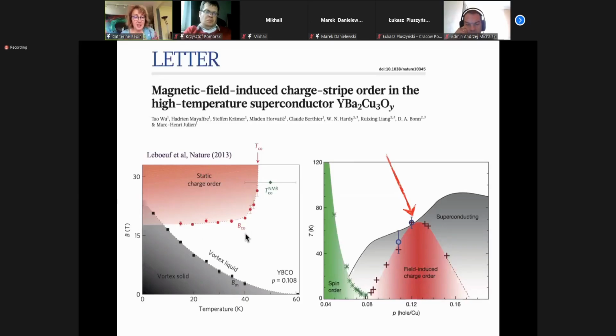So this is typical of what we call, if you have antiferromagnetism and a magnetic field perpendicular to it, a spin flop transition. Namely, it's not really a phase transition, it's more like a first order kind of flip. You know, the spins are, let's say, in the XY plane. You put a magnetic field perpendicular to them, and suddenly, when the magnetic field is big enough, the spin starts to flip in the direction of the magnetic field. So that was very encouraging to us because, of course, we don't have spins and magnetic field, but if we have pseudo-spin, we could have a pseudo spin flop transition over there.